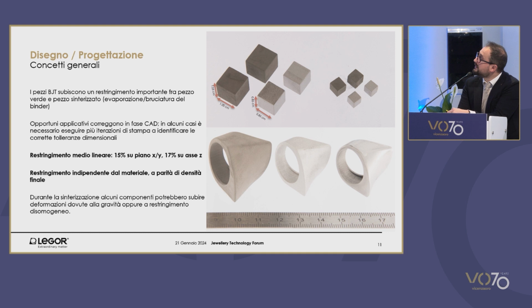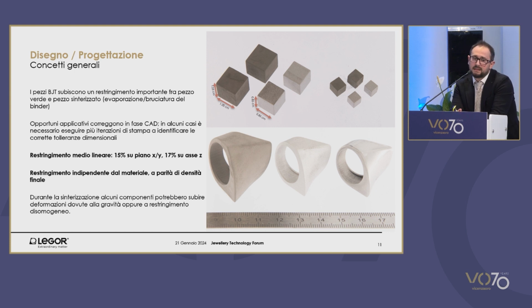I still have to consider the shrinkage in time due to the fact that my initial item has a certain size during the drawing and designing phase, that must be bigger due to the fact that there is the binder as well. The item is 15% larger when I'm printing it compared to the final item on the XY plane, and 17% on average on the z-axis, which is the axis on which the binder is deposited. So if the object has been perfectly sinterized, these parameters are independent of the type of alloy.